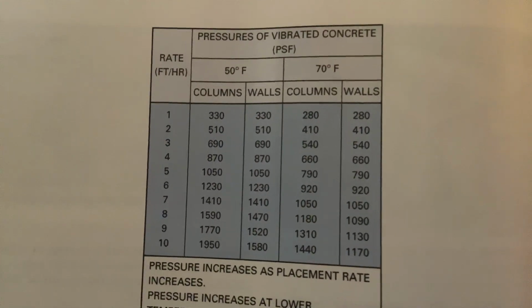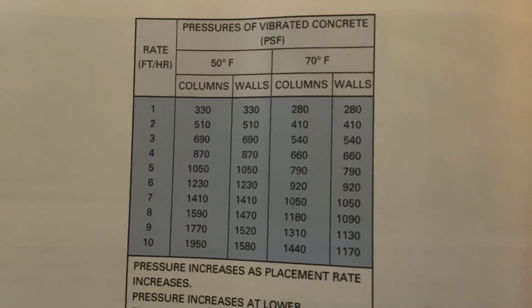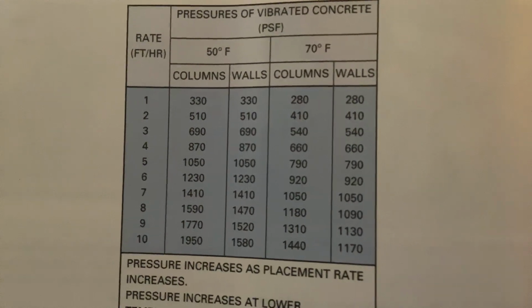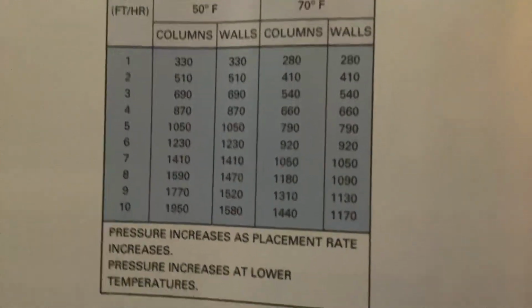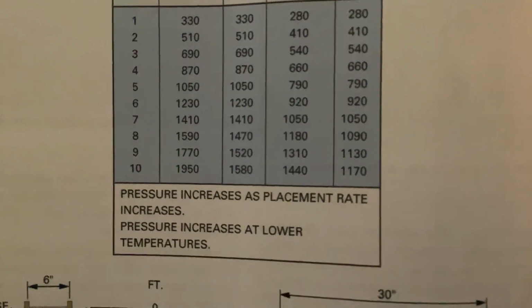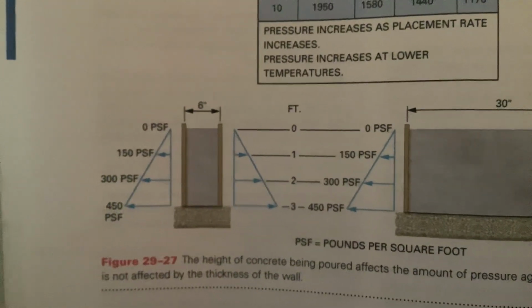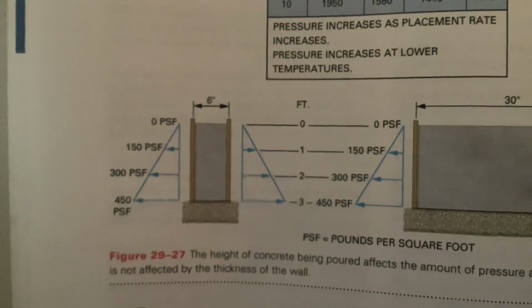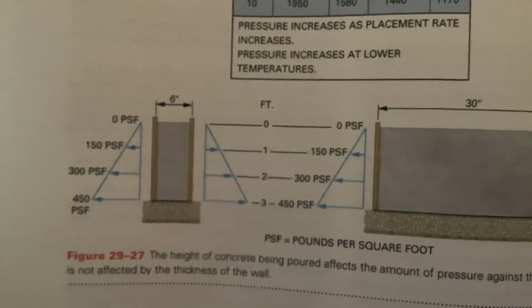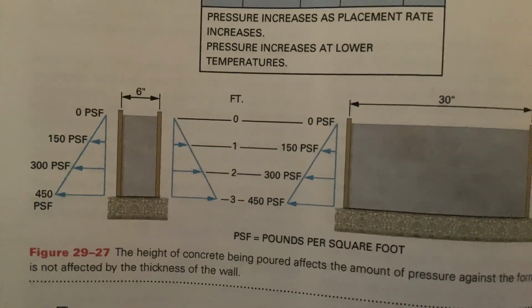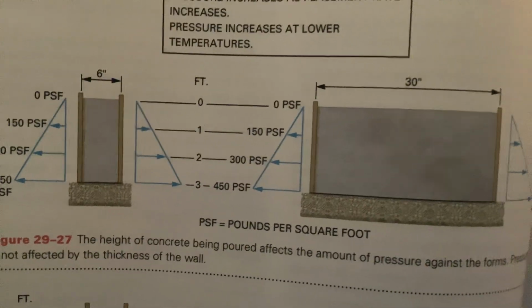Pressures of vibrated concrete. Rate in feet per hour. Columns, walls. Pressure increases as placement rate increases. Pressure increases at lower temperatures. 0 psf, 150 psf, 300 psf. 300 pounds per square foot, 450 pounds per square foot.